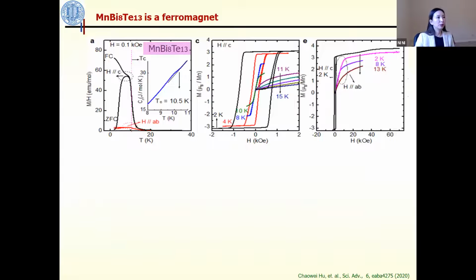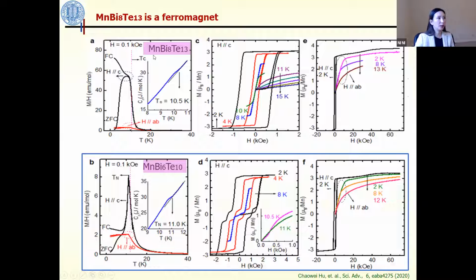So now, if we look at 1813, we immediately see a difference between 1813 and all of the others. Instead of having a little cusp as in the 1610, which shows it's an antiferromagnet, for 1813 we saw a very large bifurcation in the zero field cool and field cool data. Also, if you look at the field cool data, the magnitude is about 10 times larger than 1610. Furthermore, the MH data shows a typical hysteresis loop for a ferromagnetic material. There is no indication of a spin flip transition here. So from our measurement, it looks like ferromagnetism rather than antiferromagnetism.